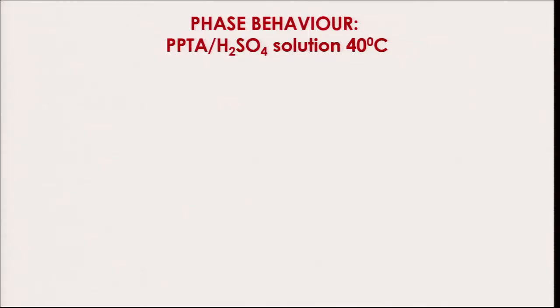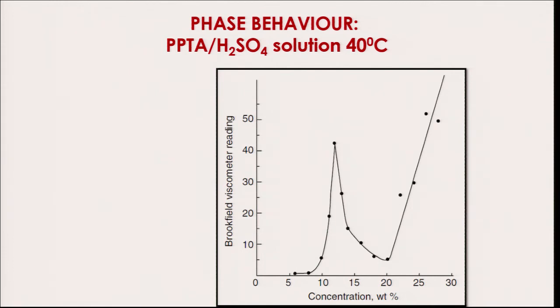Let us look at the liquid crystal behavior, or the phase behavior, of the solutions of these polymers. In this particular case, I am showing you PPTA, that is Kevlar or para-aramid, solution in 100% sulfuric acid at a temperature of about 40 degrees. On the x axis I have concentration, while on the y axis I have Brookfield viscosity, right. These structures show the rigid aromatic structure. When I increase the concentration, the viscosity increases, which is very normal for any polymer, for any material.